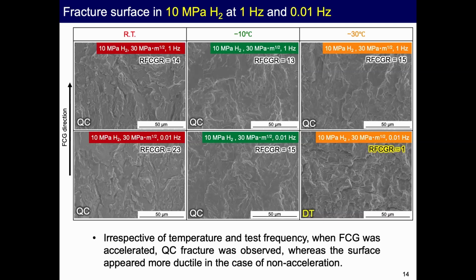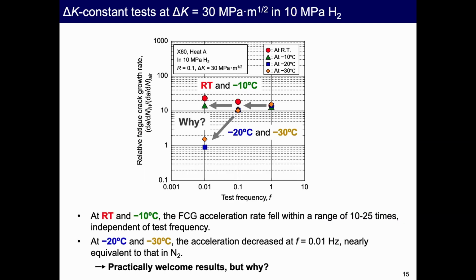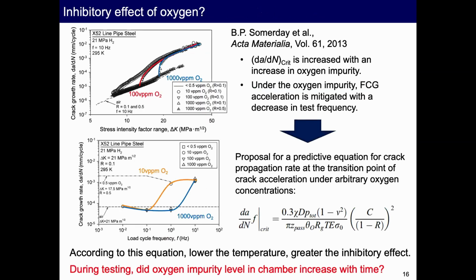We made a fractographic observation, but I skip it. But the question is why? Why do we have this kind of deceleration at lower frequency? The first possibility that comes to mind might be the inhibitory effect of oxygen impurity. Maybe everybody thinks about it. As you may know, the Sandia team reported such an impurity effect. And they reported that the transition point is increased with an increase in the oxygen impurity.